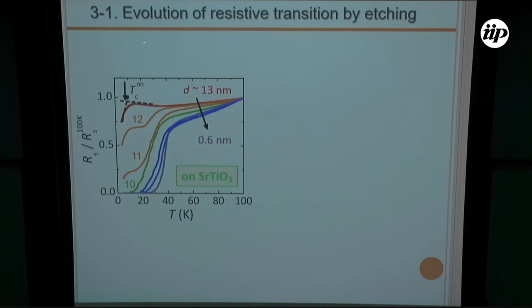So first, I would like to show the evolution of the resistive transition by etching. This is a typical example of the resistance versus temperature curve as a function of thickness on the strontium titanate substrate. In the initial 13 nanometer thickness, the TC onset around 9 Kelvin is almost the same as the bulk value. But with decreasing thickness, the transition becomes two-step, and around 10 nanometers, it changes to a one-step transition, meaning that superconductivity developed in the whole sample. With decreasing thickness further, at 0.6 nanometer, which corresponds to 1 unit cell, maximum TC with the onset above 40 Kelvin occurs. So this implies that our top-down method is working very well, reproducing the previously reported bottom-up method.